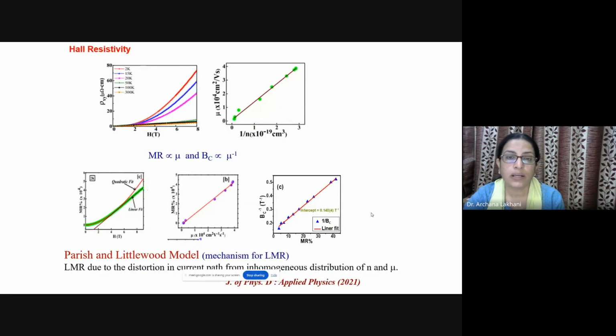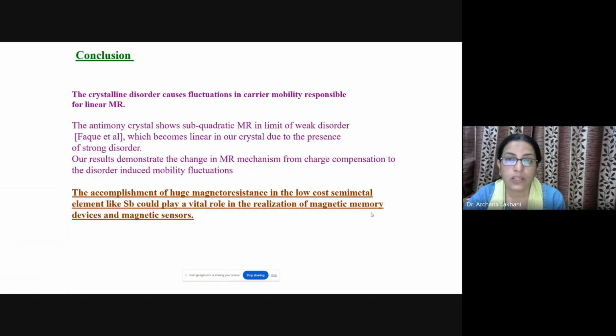So having such a large magnetoresistance in such a simple, cheap material like antimony is very encouraging. The crystalline disorder in this particular material causes carrier mobility fluctuations, which is responsible for this linear MR. So the accomplishment of such a huge magnetoresistance in such a low cost semi-metal like the element antimony could play a vital role in the realization of magnetic memory devices and magnetic sensors.